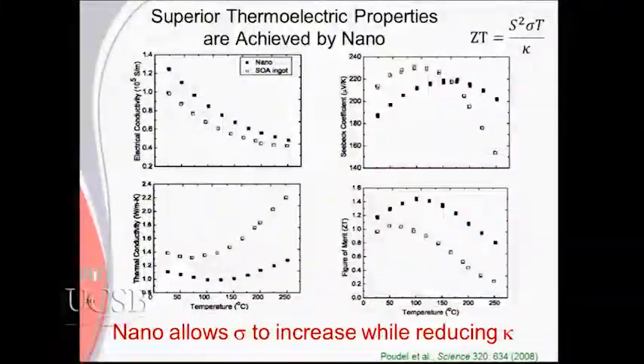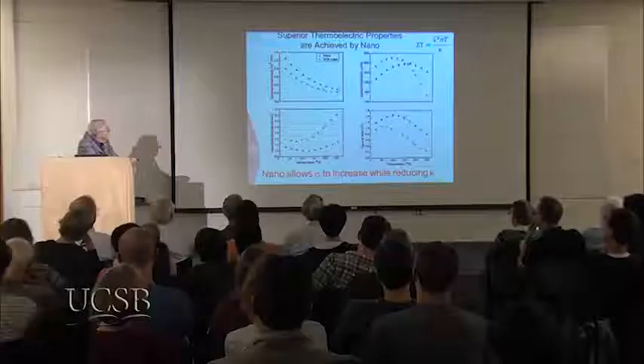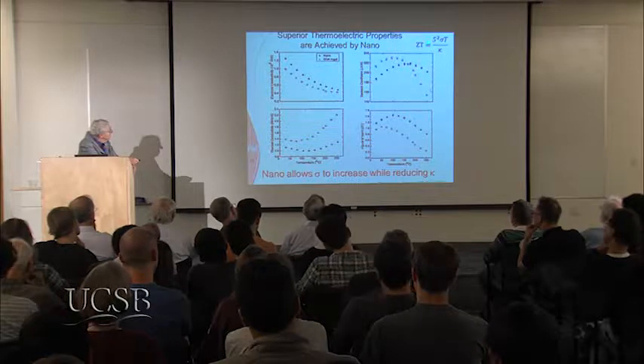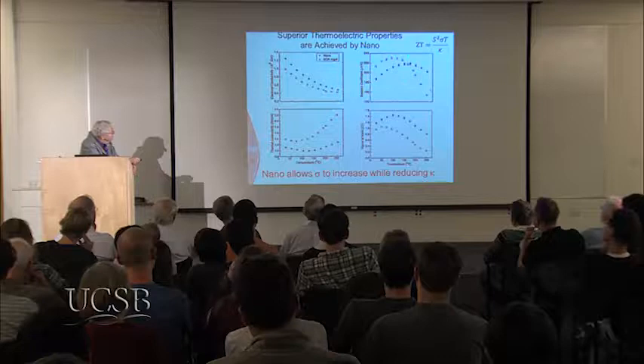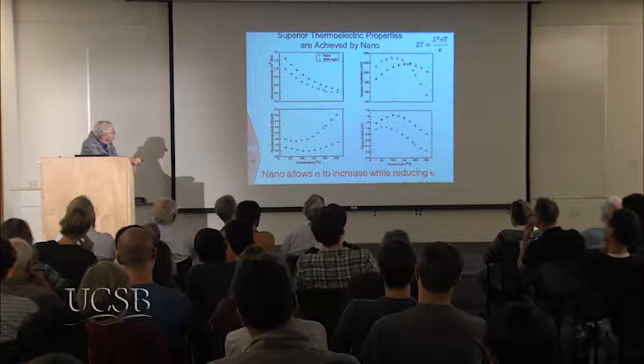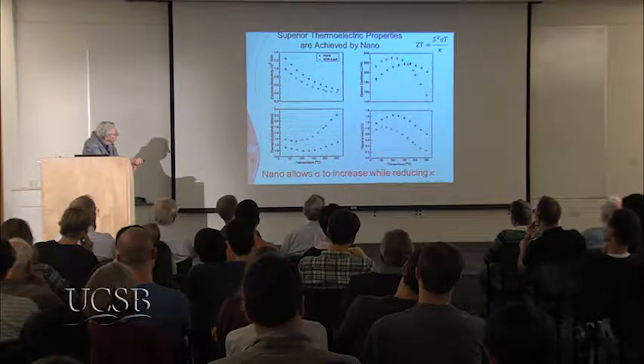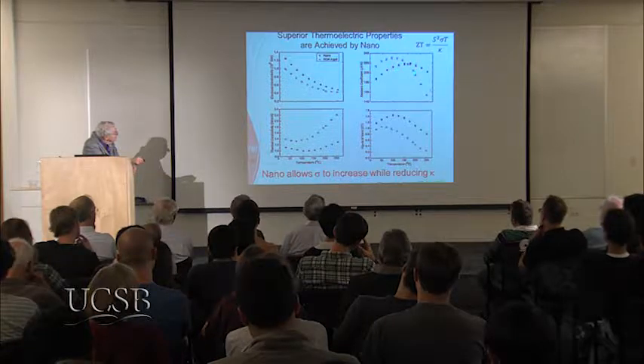Now I'll show you some of the results. The thermoelectric figure of merit is shown here. So the idea is we have to increase the Seebeck coefficient. So Seebeck is over here. And, well, we weren't totally successful. Here's the nano, at the higher temperature here, about 150 C, it works. And here it doesn't work. But all the other factors worked well.